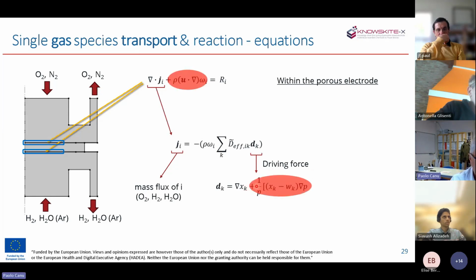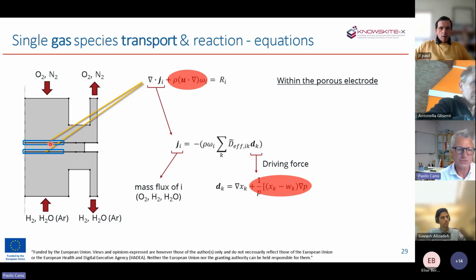But what has been shadowed now are the contributions that are negligible within the electrodes. So the convection, the transport of species because of the overall movement of gases within the pores, is negligible because the velocity inside the pore is indeed small. So diffusion is ruled by the gradient of concentration. Oxygen will penetrate into the electrodes just because you expect a higher concentration close to the electrode surface compared to the concentration further down within the electrode.